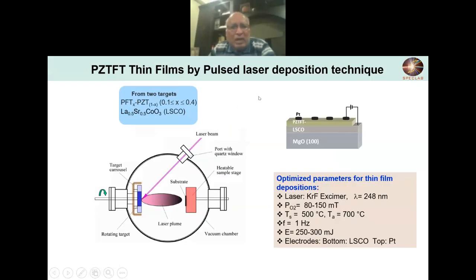All this work was done on ceramic so far, so we decided to make some thin films of these materials. One of the thin films that I'm reporting here is the PZT-PFT thin film. That is made on the MgO substrate, and LSCO was the bottom electrode for electrical measurement purposes. LSCO is not magnetic, so it was okay. And the MgO was the substrate. So here are the pulsed laser deposition parameters for depositing the material.